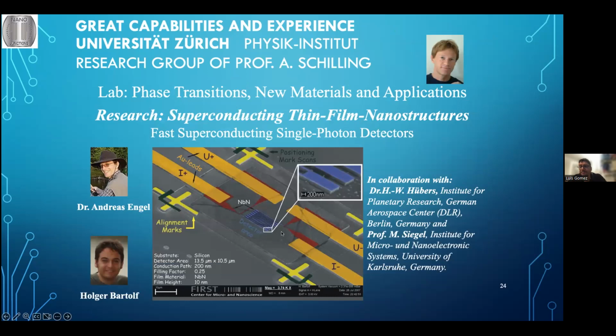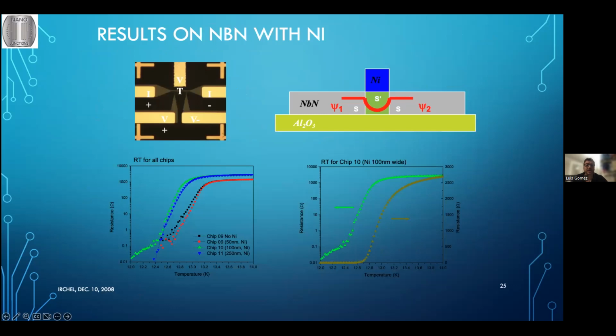and basically a system to create very narrow photon detectors. This was published by then. We used niobium nitride, a very interesting superconductor, and Holger worked really hard to get these islands very narrow, about 15 nanometers. This just lasted a year, and then I went on to be an assistant visiting professor there, and I worked on a similar system, but this time with niobium nitride and nickel. That's a really cool experiment.